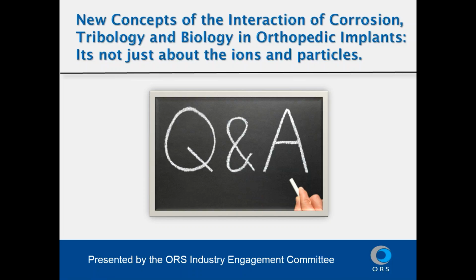No, it's really not likely and not possible. It's very clear when you see damage that's from a mechanical nature, where the deformation pattern on the surface will be evident. These are not deformation-based patterns that are arising. And they're far too fine and on a biological scale than they would be from some surgical iatrogenic source.